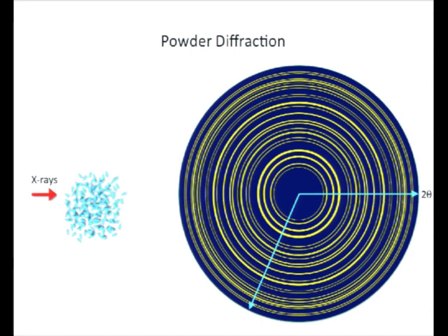The problem, of course, you can see if I now overlay the single crystal pattern. And just concentrate on these four reflections. They all have approximately the same distance from the origin. They have approximately the same 2 theta value. They are under the same peak in the powder diffraction pattern. So we have these four reflections, and we only have the sum of their intensities. If we only have the sum of the intensities, we have an ambiguity in the individual intensities. And this is what is known as the reflection overlap problem.